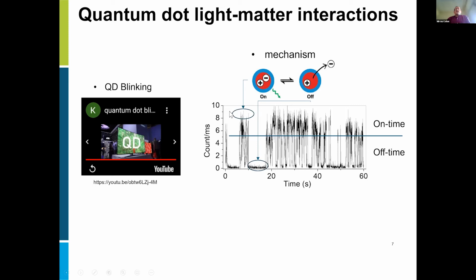So we have an on level here, but sometimes the electron can be ejected from the core, so it can be trapped at the surface, and the quantum dot becomes charged and undergoes non-radiative recombination. In this case, we will see something which we call the off state or off time. And this process is reversible. This is what the arrows here show, and it goes on and off and on and off. And if we look at the picture here, on the time scale, we can see that it has a distribution of off times and on times.